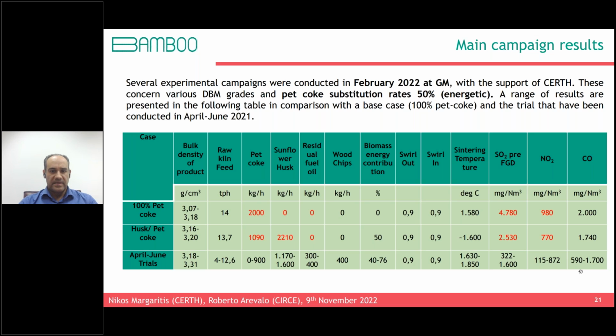This table summarizes the main results of the experimental campaigns that were conducted in February 2022 at GM with the support of CERTH. These concern various DBM grades and petcoke substitution rates of 50%. This was the maximum substitution rate that was achieved during these experimental campaigns. And you can see also the comparison of 3 cases.